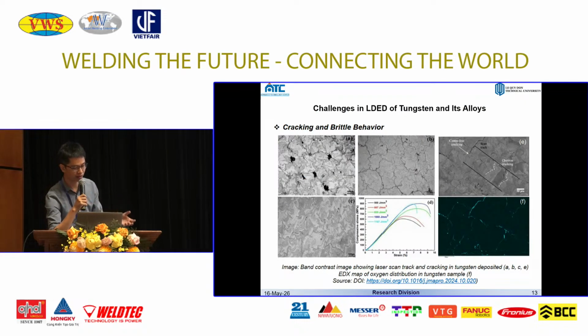It sounds promising in theory, however, printing tungsten and its alloys is not easy at all. First is cracking and brittle behavior. We know that tungsten has a high ductile-to-brittle transition temperature, so the rapid heating and cooling cycles from laser processing create massive thermal stresses, leading to solidification cracking and intergranular fractures.